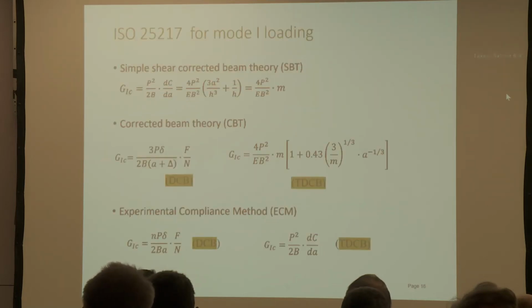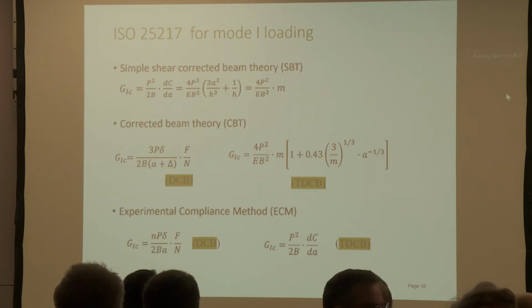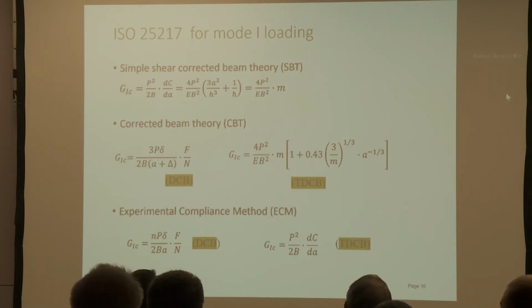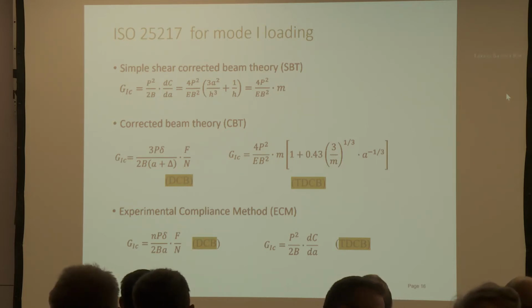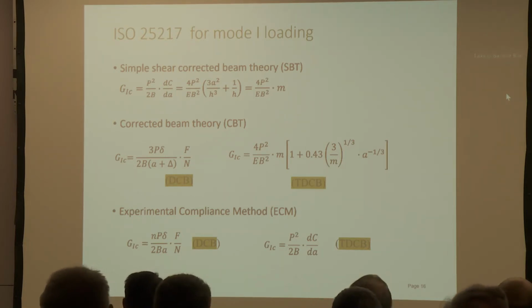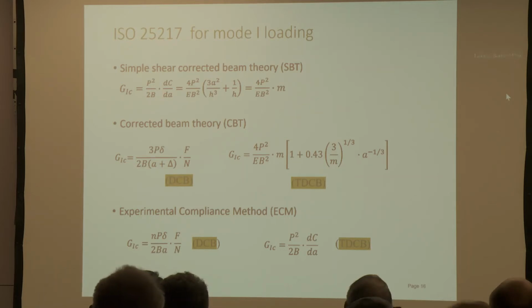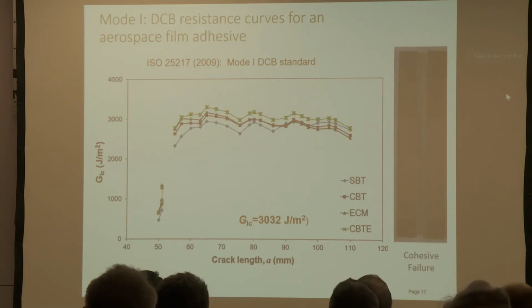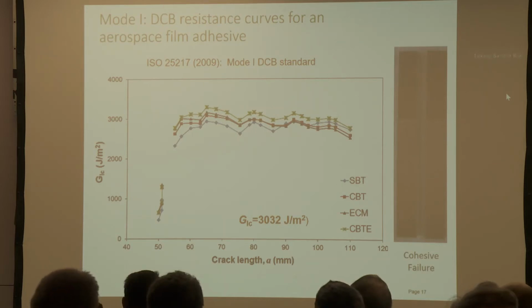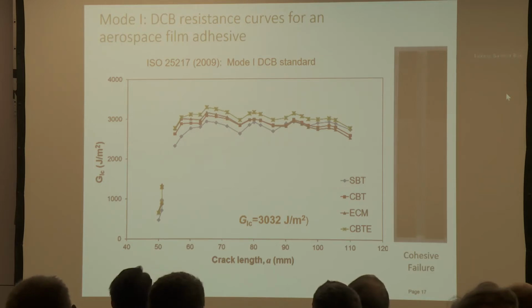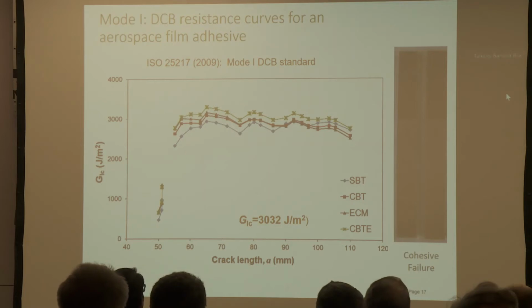So in the ISO we were developing, we implemented corrected beam theory, which included a root rotation term and corrections for large beam deflection and end block stiffening, and also the corrections that I just mentioned to the tapered double cantilever beam. And we implemented a simple shear corrected beam theory, a corrected beam theory, and an experimental compliance method. So in terms of fracture resistance, those methods and determination of G via the three methods work well.